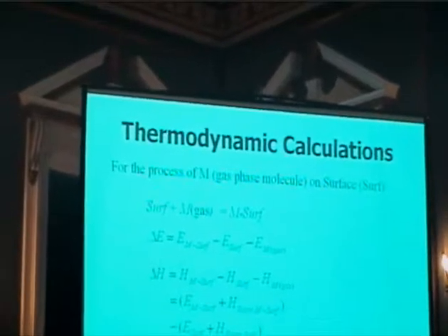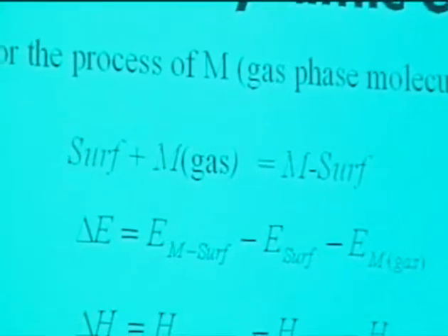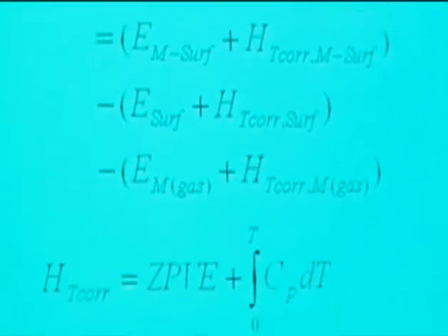Now, in order to do the complete or the rigorous approach to understanding the thermodynamics of adsorption, we need to apply a little bit of thermodynamics here. In all of our calculations, we just do a simple material or energy balance where we're calculating the difference between the adsorbed state and the clean surface and the free molecule. I'm not going to go through any of these equations in great detail, other than to say that we're correcting all the ground state energetics that you calculate with DFT for temperature, where the temperature correction involves a zero-point vibrational energy term as well as a heat capacity term.